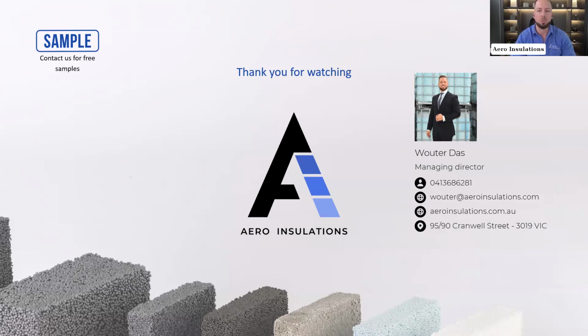And they get there currently with cellular cement or foam cement that they use. But that needs about 480 kilos of cement per cube to reach a compressive strength of between 1 and 2 MPa. Now we can get there with 260 kilos. So that's a reduction of 50% in their sort of environment. Now I haven't really explored the comparison between compressive strength or differences between filling up with soil. This is just going from the mining backfilling sort of proposition to roads. That would be a natural progression in my opinion.